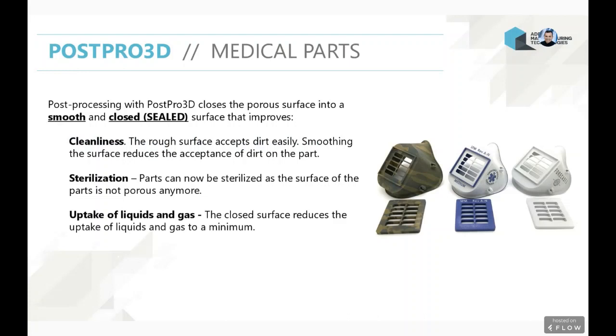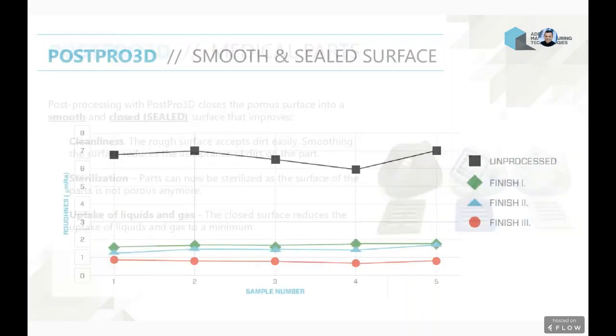So, as far as the PostPro3D technology goes, when a part has been printed out of a multi-jet fusion process, for example, it's got a specific surface roughness value that, depending on the orientation of the part or depending on the nesting and the temperature conditions, for example, of your process, you are going to achieve a specific density out of your part.